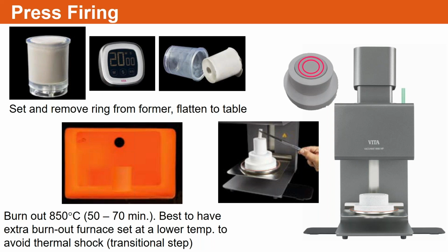So a lot of the production laboratories, what they'll do is they'll have a dedicated furnace that's a little bit less in temperature. The final burnout temperature that we use is 850, but maybe you have one at 600 degrees or 700 degrees. And you leave it in that first to initially start making sure that your rings elevate to the right temperature or close to it, and then you move it over. You kind of tap it as you take it out to make sure that any residue's out, and then you move it over to your final burnout furnace at 850, and then at that point you start adhering to the time that it's in there, 50 minutes for a small ring, 70 minutes for large ring.